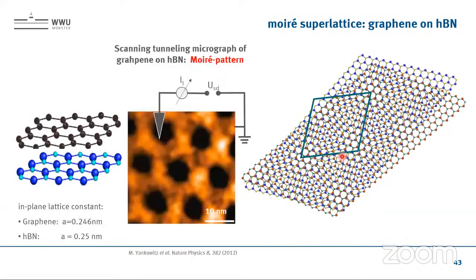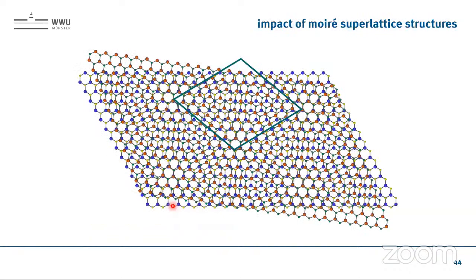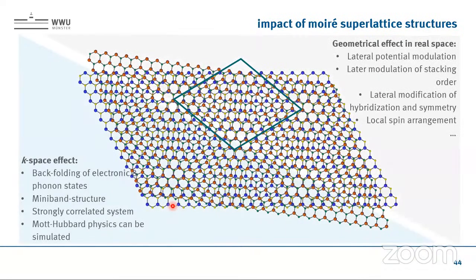So first of all, let's see if it's true. Yes, it's true, because it has been proven: if you combine hexagonal boron nitride and graphene and do a scanning tunneling microscopy image, you see very well this moiré pattern. So that's not the hexagonal structure of the individual lattices. The scale bar is 10 nanometers, it's really the moiré pattern. And now with that, there are 2 directions, let's say, where geometric effects in real space from this moiré pattern, and one is k-space effects where the band structure is influenced.